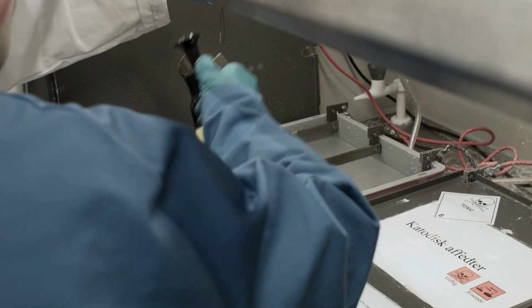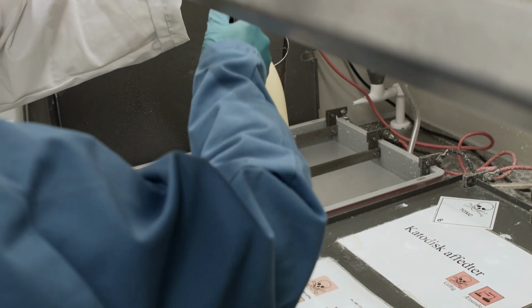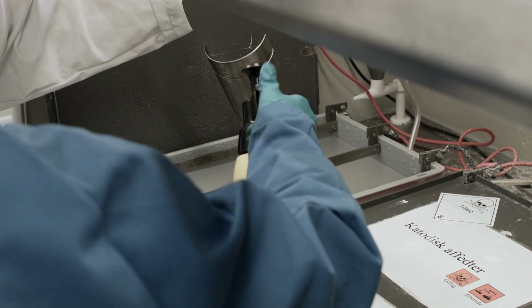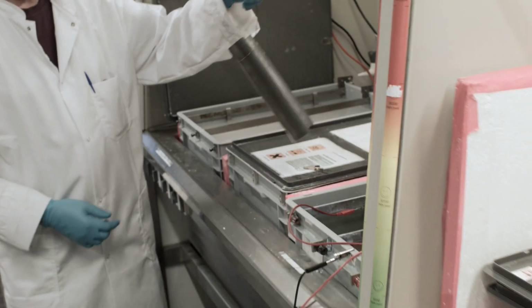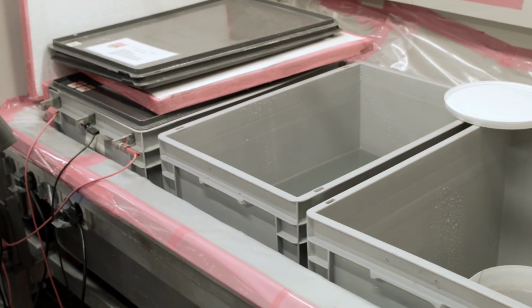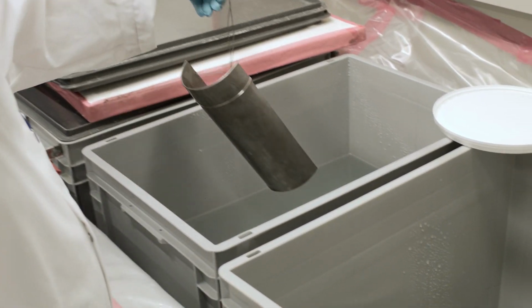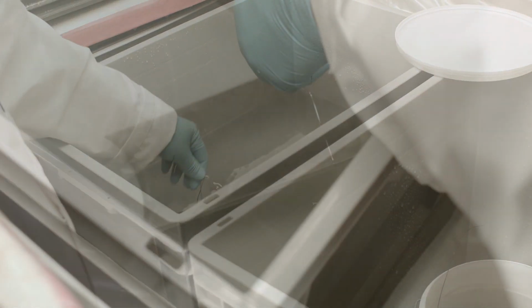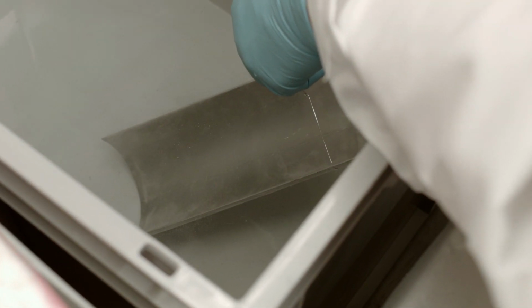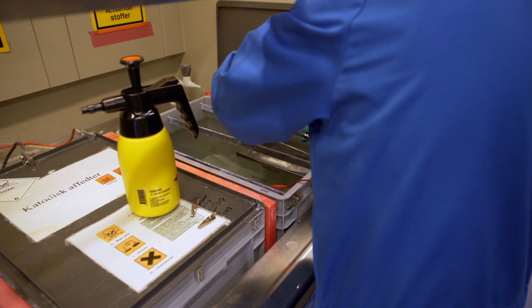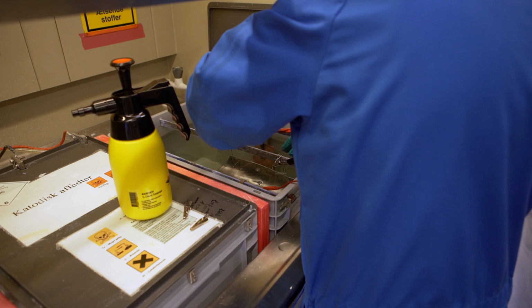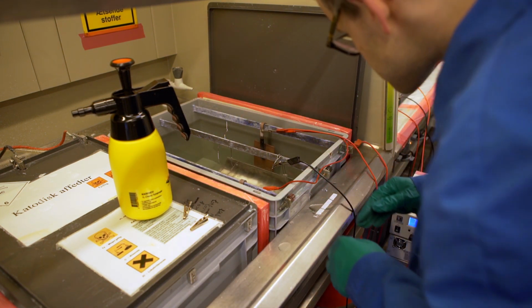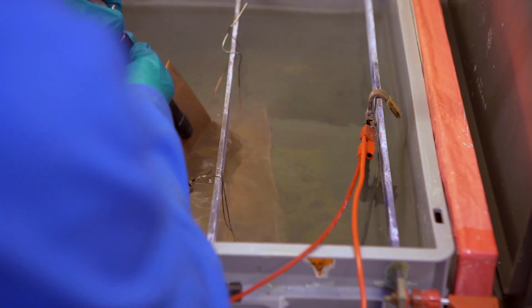After degreasing, the part is rinsed with water and moved to the final acid bath. To ensure the best possible adhesion of nickel to our parts, we actually deposit a thin layer of copper first.